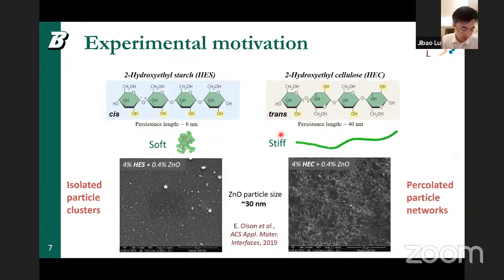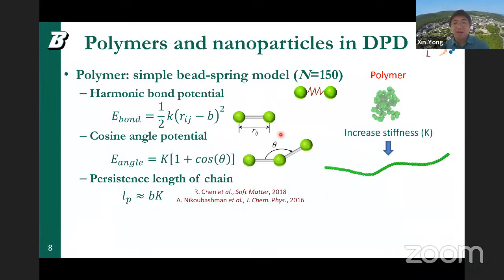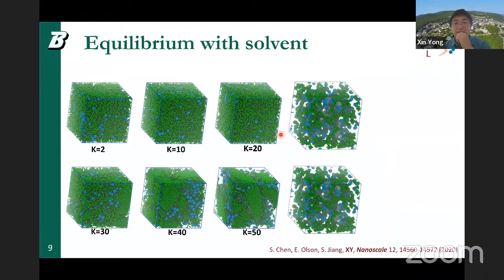Okay. So have you ever characterized the viscosity of the composite? That's a great question. Unfortunately, the answer is no. The reason is that characterizing viscosity for this system is actually quite expensive, because the typical way is using Lees-Edwards. You have to shear the box, and then you have to measure G prime and G double prime.